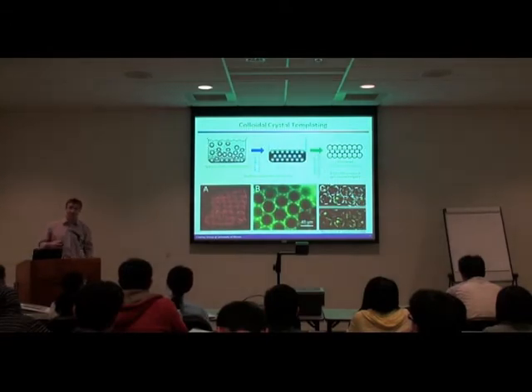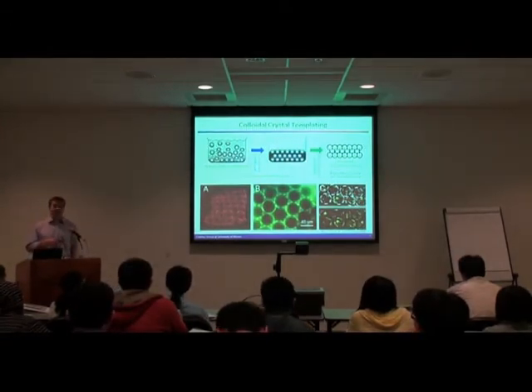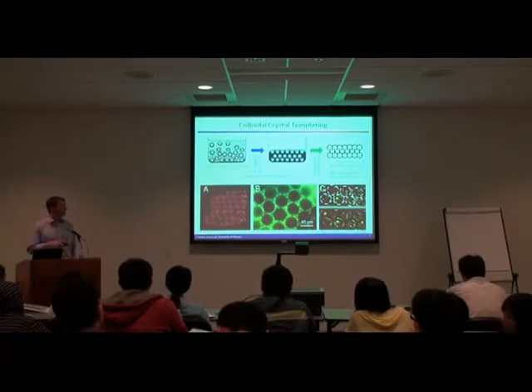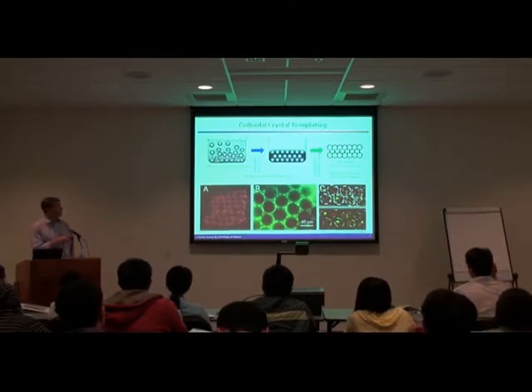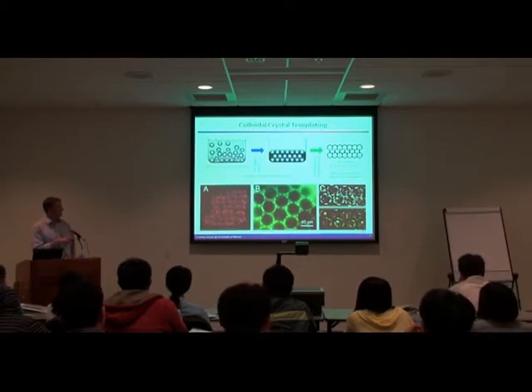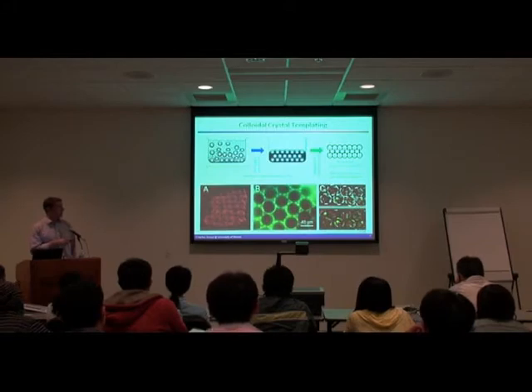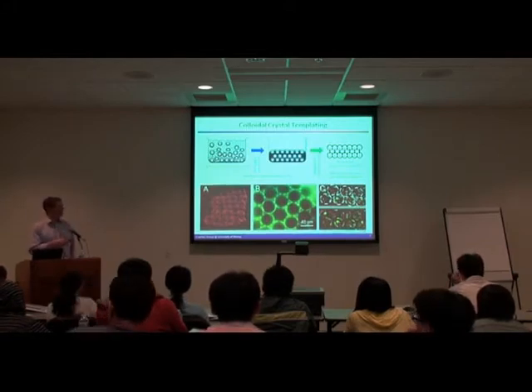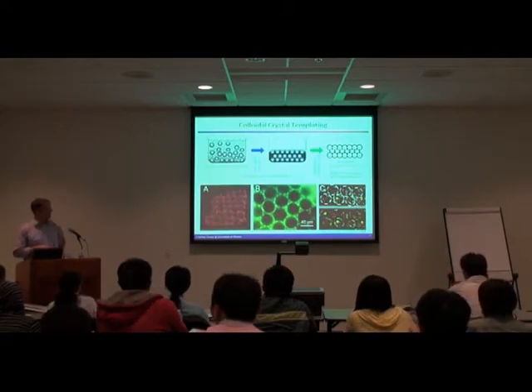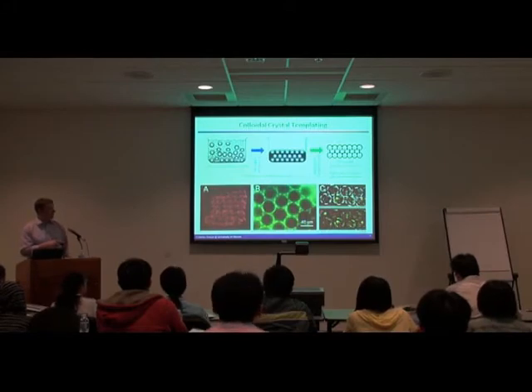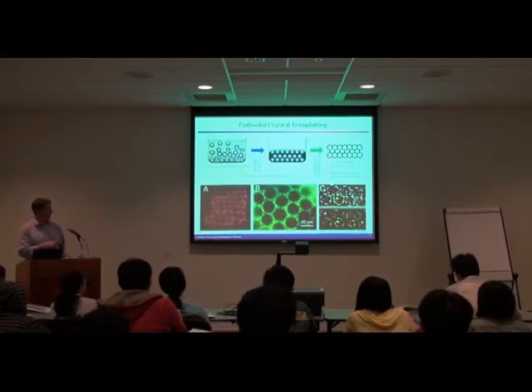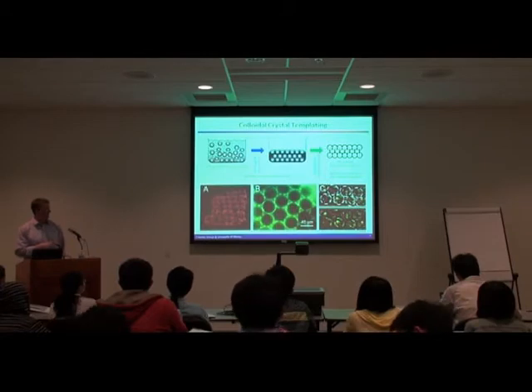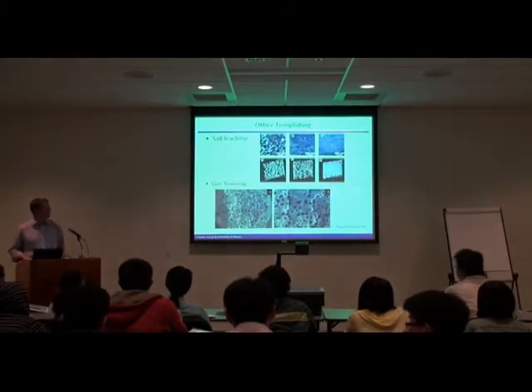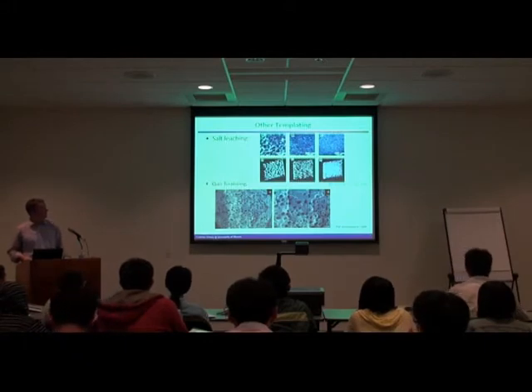There are lots of other ways in which you could generate similar cellular materials. I didn't want to give the suggestion that freeze drying is the only way you could do it, so I decided to put up a couple of other examples of groups that have developed similar cellular materials. One of the classic examples is colloidal crystal templating, where you take some spherical templates, sinter them together to form a packed structure, fill in the space in between with some biomaterial, and then leach out the spheres. What you end up with is a porous structure that is a little bit more regular than our collagen-GAG scaffold. Looking at a confocal microscope image through it, you can see this nice regular pore structure where you have a great deal of open pore nature, some solid, and interconnections between the pores. Other templating approaches have generated similar materials, although not nearly as uniform. Some of those examples are salt leaching and gas foaming.